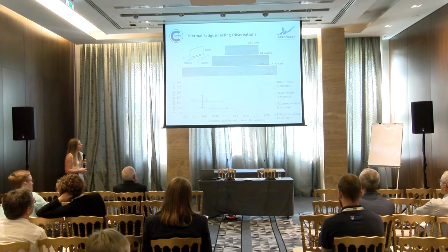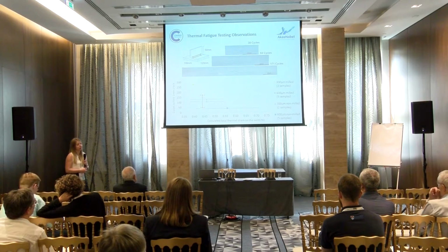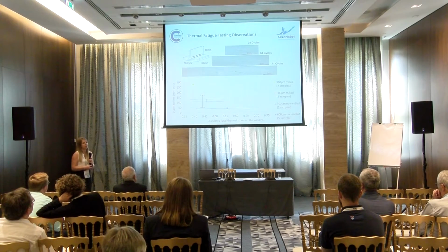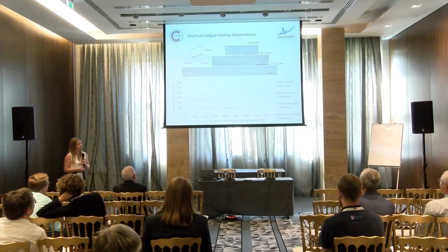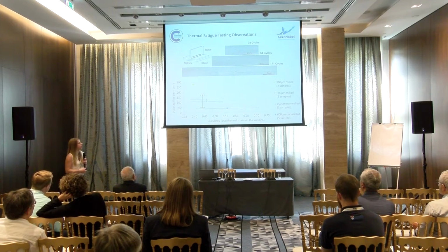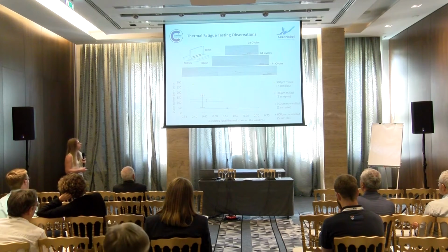So the 600 non-milled weld condition will have a huge possible strain range because its coating thickness could be anything between 600 and 1,000 microns, and its weld fillet radii anything between 0.5 and 3 millimeters. But if we apply 300 microns onto a non-milled weld, this range reduces, and then the range is reduced even further as we apply the coatings to welds that have a constant 2 millimeter radius. So we can just see this trend appearing, that you've got very, very few cycles to first millimeter crack for all of the thick samples applied to an uneven substrate.